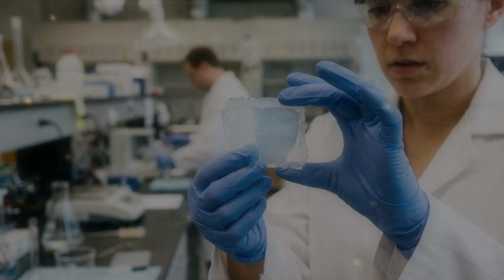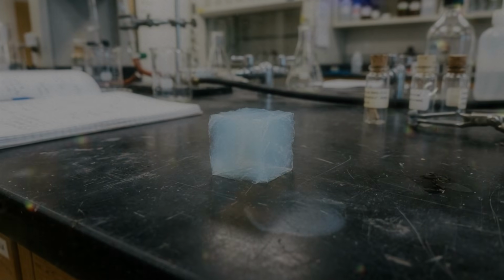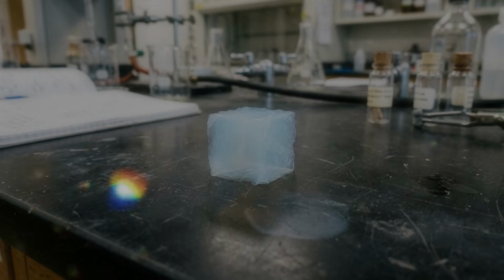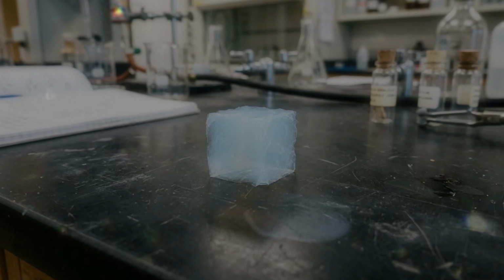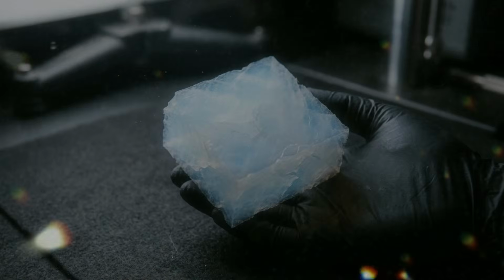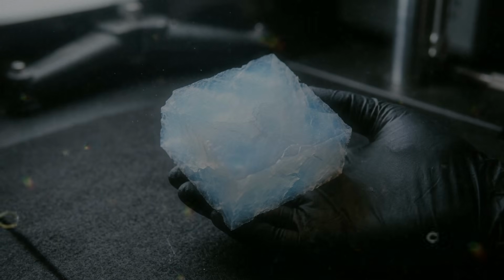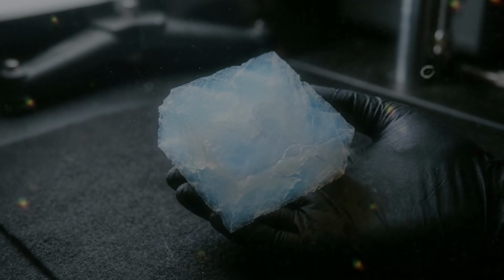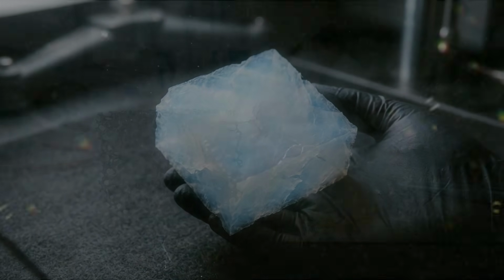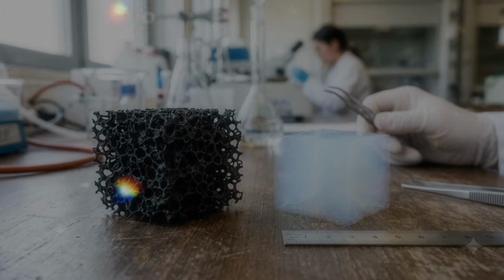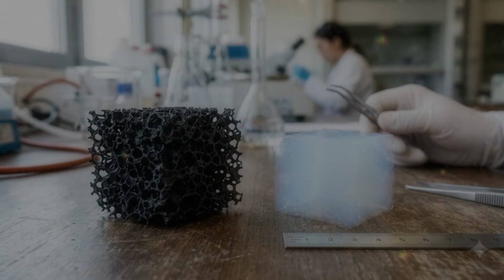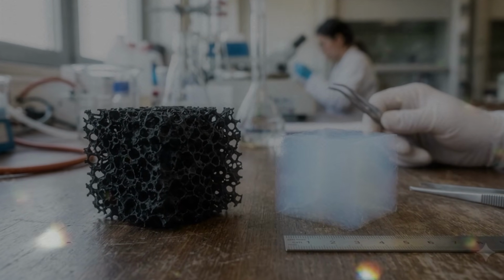Impurities can change the outcome. Dust, salts, leftover reactants, or small differences in water quality may affect gelation. Temperature variations across a large mold can create uneven pores. Bubbles trapped during mixing may become cracks or cavities. Tiny defects can grow during drying until the final object breaks.